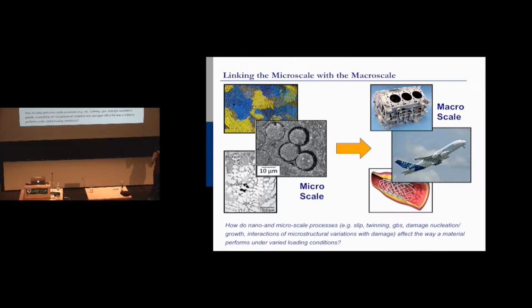The mechanism changes. In that very high cycle fatigue regime, above 10 to the 9th cycles, the mechanism becomes microstructural hotspots that cause an initiation of damage and blow out the material. But you have to figure out what those hotspots are because we don't want to process our materials to have those. So how do you access that? A lot of the stuff that we do, we build these novel methodologies to access regimes and make experiments that have not been done before.